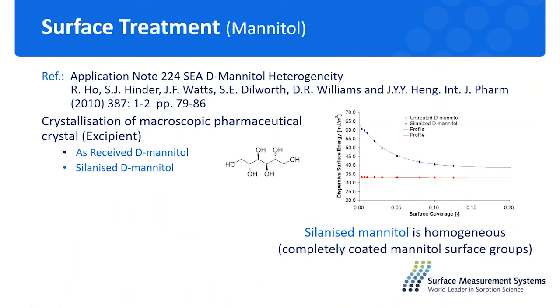So the first case study I have here is a surface treatment on mannitol material, where we have the as-received non-treated mannitol, and we did a silanization process on our mannitol material. So we measured the surface energy of both materials, and we have our energy profile on the right-hand side. The blue line here is the untreated D-mannitol, which starts with the high energy sites at low concentration and then goes to the low energy sites at high concentration, or high coverage. So basically for this untreated D-mannitol, the surface is very heterogeneous, with a large variation of the surface energy as a function of surface coverage. And after the treatment, we have the red line for the silanized D-mannitol.